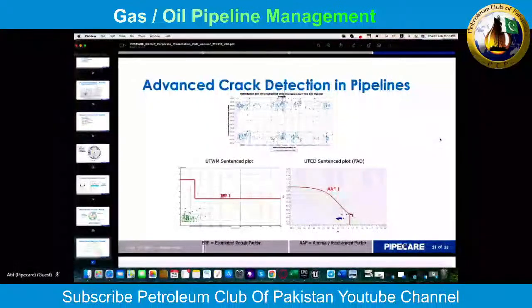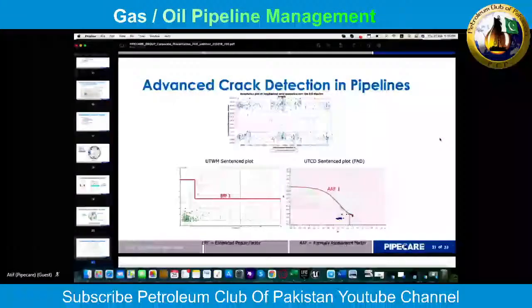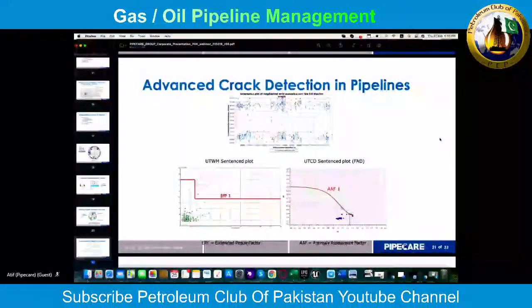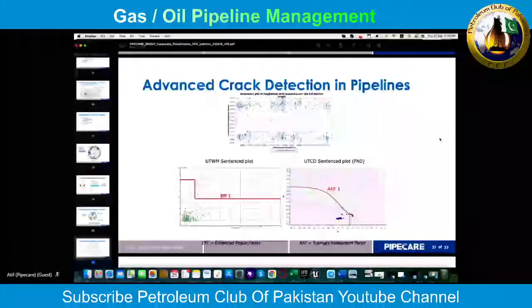What you get from a crack assessment is the same type of report that you are used from a metal loss assessment. There's one difference, which is the sentence plot. What you are maybe familiar with from UTWM or also from MFL or TFI inspections is the sentence plot on the lower left with the typical ERF curve. ERF curve equals 1 means this is the repair line where features need to be taken care of.